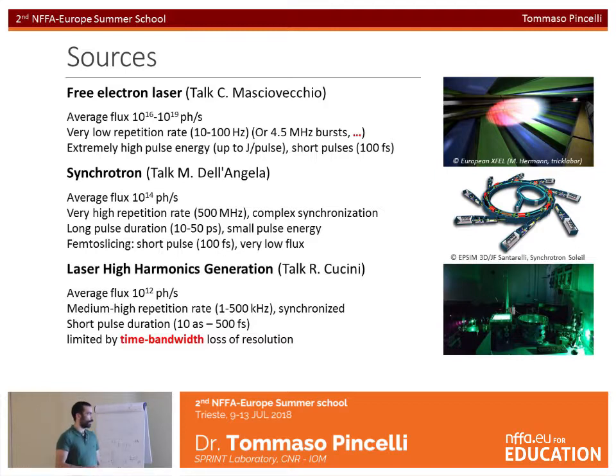Then you can use synchrotrons. They have fluxes up to 10 to the 14 photons per second, so lower than this, but they do it with a very high repetition rate, up to 500 megahertz. It's complex to synchronize a synchrotron with a laser. They have generally long pulse durations because the duration of the pulse is set by the length of the bunch of electrons that is turning in the synchrotron. And we have a very small pulse energy.